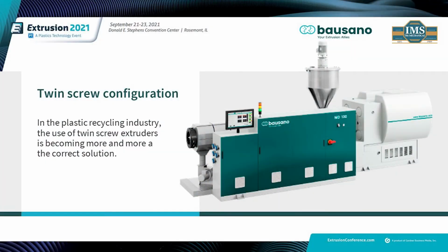So the wear and tear will be higher on the screw, which will be much more evident in a single screw extruder. As the screw accelerates in its wear, you'll begin to make inconsistent product. In the plastic recycling industry, the use of twin screw extruders is becoming more and more a winning solution to common processing issues and challenges. For this reason, today we are focused more on recycling with a twin screw extruder.